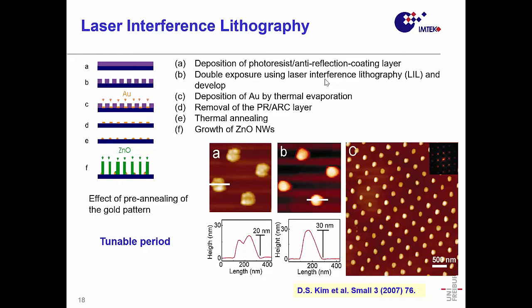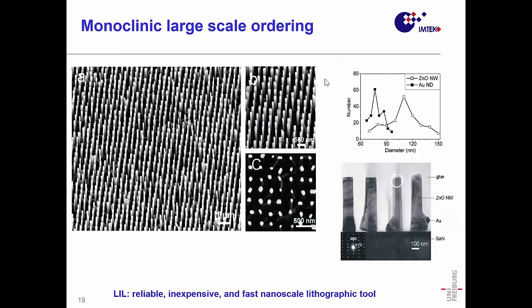The gold pattern is like you see it here in A. That's an AFM image, measured by an AFM tool. It's not completely spherical, it has different heights. If you start to grow with that, you end up with three, four small wires. To get one pillar out of each, you have to pre-anneal it again, making this wetting, de-wetting process, and then you can grow that on a large scale.